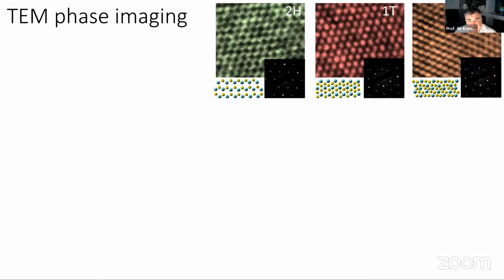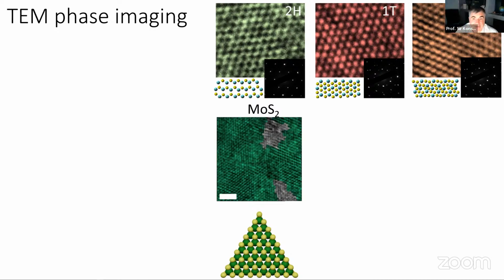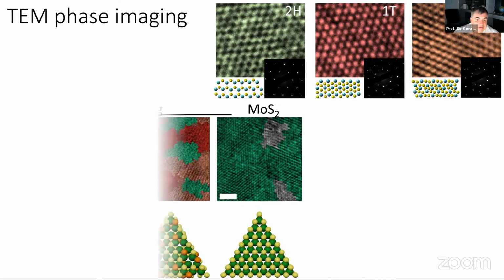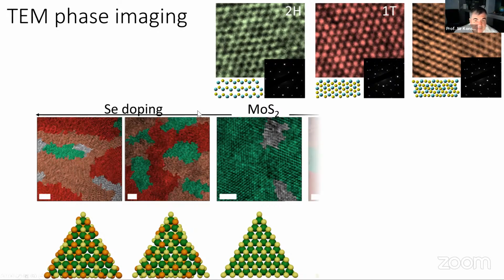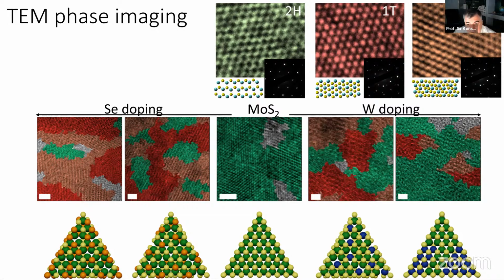those materials, you start to produce some defects in those materials. They don't only produce defects, but they change their phase structure. Like MoS2, very simple material, but it can exist in a variety of different phases. Meaning the relative position of molybdenum and sulfur, and you start adding individual defects, and suddenly there is a phase transition, and you get into a completely new crystal with new properties. And this idea that you can control the properties of materials by changing their phases and by controlling the phase transitions really brought us to the next topic of our research.